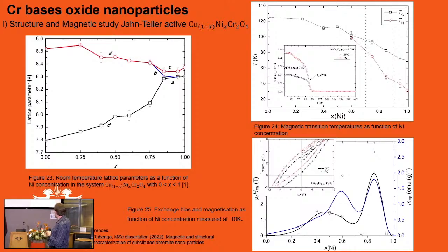Now there's two fields here. It's what's called zero field cooled, no field applied. You measure then at low temperature. And the next one you apply field. If you see more of a shift, it is a pointer towards exchange bias in the system. This is typically only seen in thin films and has been used successfully in thin films, for example in hard drives, again to use as a switching mechanism. But this is in a nanosystem, a powder. This copper nickel is a powder that we make from liquids in the lab.